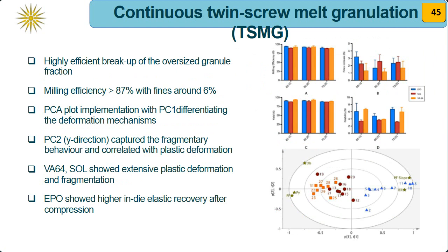Also, during the study, it was found that highly efficient breakup of the oversized granule fraction can take place, and the milling efficiency, as we mentioned before, was greater than 87%, with fines for most of the binders being around 6%. This is obvious on the graphs on the right part of the slide. Also, a PCA plot was implemented with PC1 differentiating the deformation mechanism, while PC2 in the y direction was used to capture the fragmentary behavior and correlated with the plastic deformation. So for the VA64 insolubles, it was found that both present plastic deformation and fragmentation, while EPO shows a higher elastic recovery after compression.